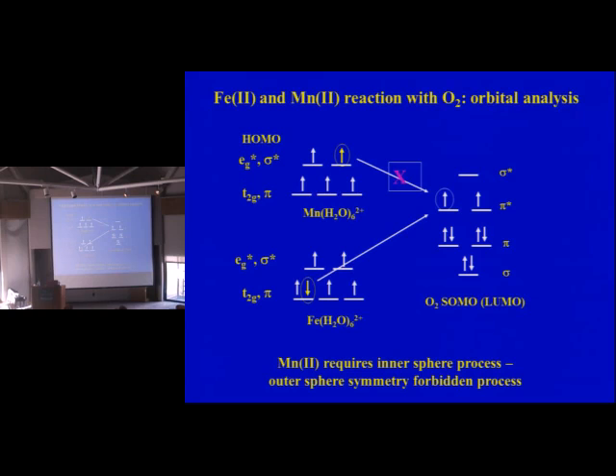So now it's an inner sphere process. So there's sort of this kinetic thing. The first electron transfer can be the controlling feature. In this case, it's a thermodynamic control if it's an outer sphere process. And that's what it looks like at low pH. As the pH increases, it's no longer iron 2-hexaaquo or manganese 2-hexaaquo. It becomes a dihydroxy manganese 2. And then you have an inner sphere process where the oxygen actually binds directly to the manganese 2. And then there's electron transfer. And it's only to that point where you get that. And that's why the thermodynamics starts to kick in at 9, because that's when you get the dihydroxide species. So you're looking at the speciation of the manganese in that case as a key. Does that answer your question, Carl? I think so.